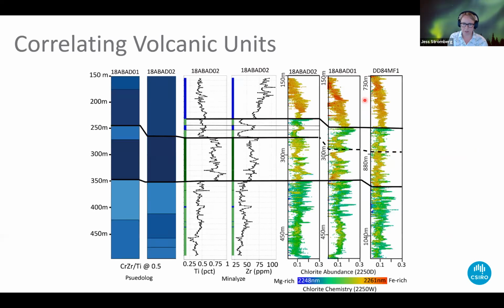And then if you want to look a little bit higher in the stratigraphy, it doesn't stick out quite as well as the previous unit that I showed you, but you can actually look at the chlorite abundance in chemistry to start looking at volcanic units. And so the top part of the Chylena formation here is characterized by iron-rich chlorite. And as you go lower in the stratigraphy, that changes. And if you look at the geochemical data, looking at the immobile elements like zirconium, titanium, chromium, you can actually pick out three distinct chemistries in the volcanic flows and correlate them across the holes. And they relate surprisingly well to these changes in chlorite chemistry. And you can see even these little changes in chlorite abundance. Those are related to individual flows within a given geochemical unit.